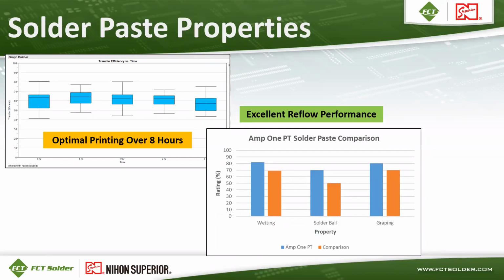We also test all of our solder pastes for reflow performance, and 3 categories that we rate them in are wetting, solder balling, and graping. In this case, I'm comparing AMP1 PT, one of our newer no-clean lead-free solder pastes, versus a comparative paste. And you can see it has higher ratings on wetting, solder balling, and graping, or improved performance in all 3 of those categories in terms of reflow.